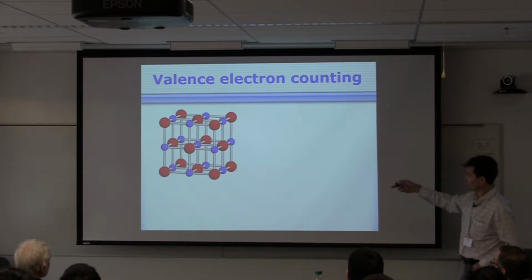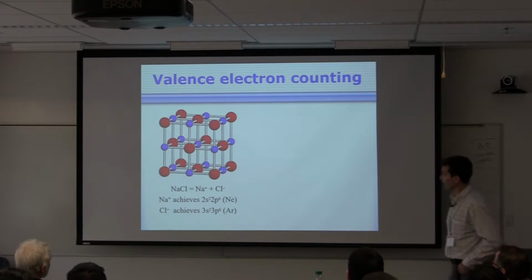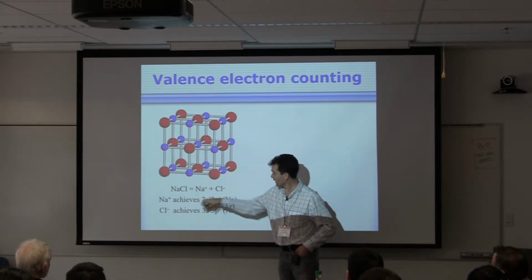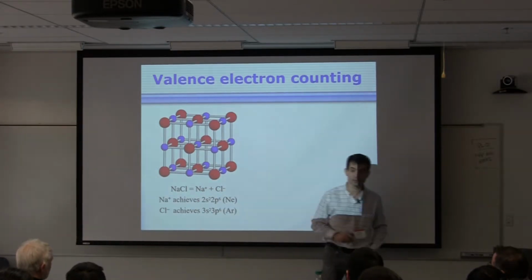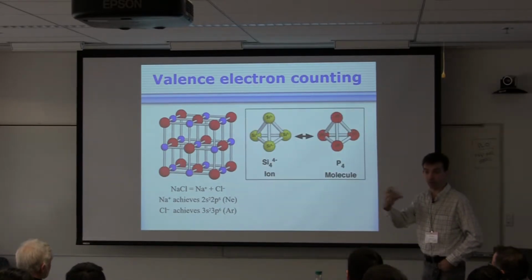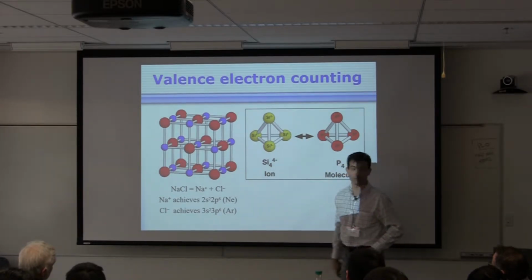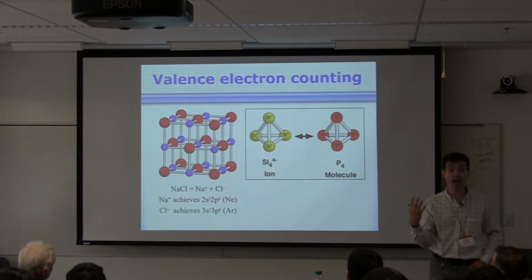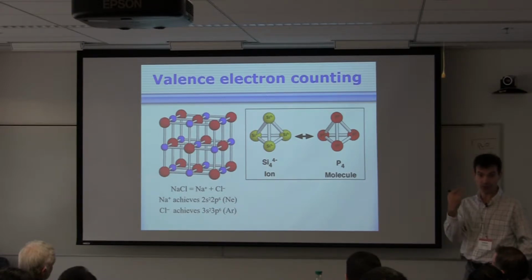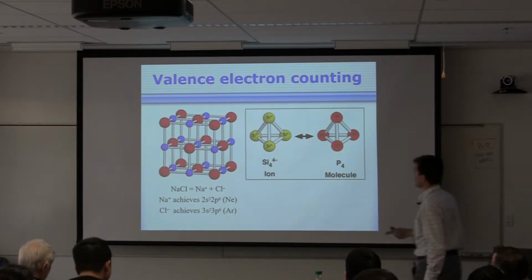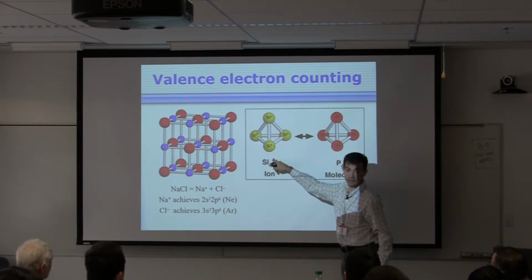So before we go into that structure, the sodium chloride: again, the sodium is electropositive, chlorine is electronegative. Sodium donates an electron, chlorine accepts an electron. This becomes a noble gas, this becomes a noble gas. In this compound that I just made, I have these units. So what I'm going to say is that I reduced silicon. Each silicon accepted one electron, and silicon was forced to form a tetrahedron. And now I'm going to call this a silicon 4, 4 minus.